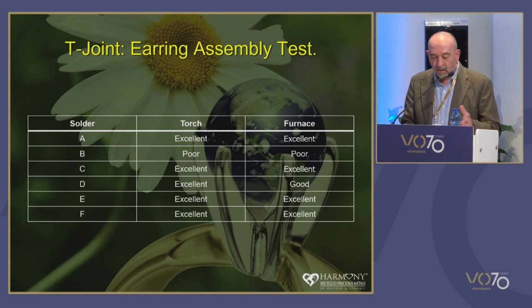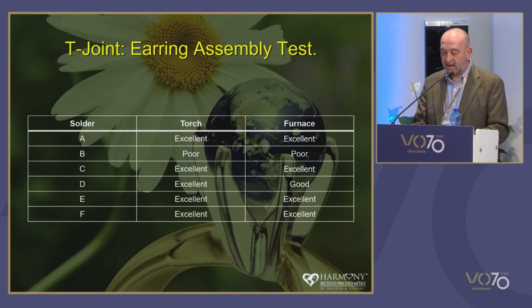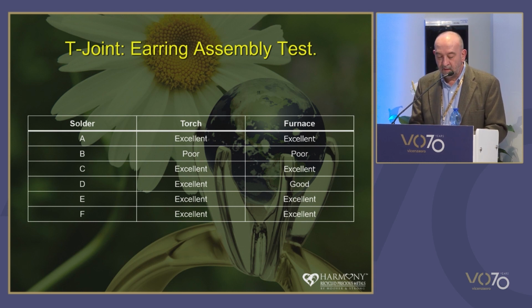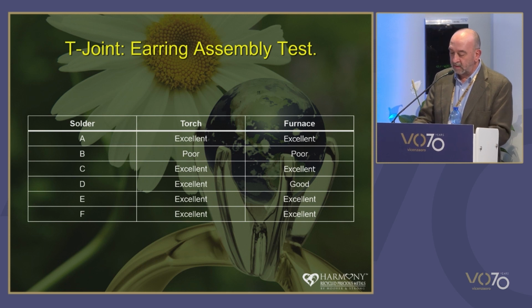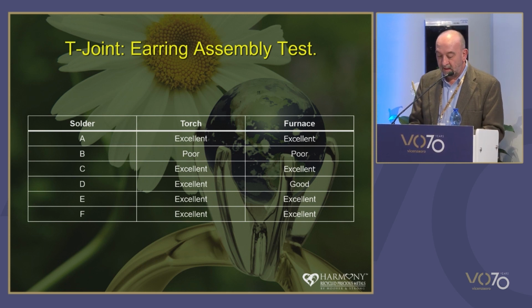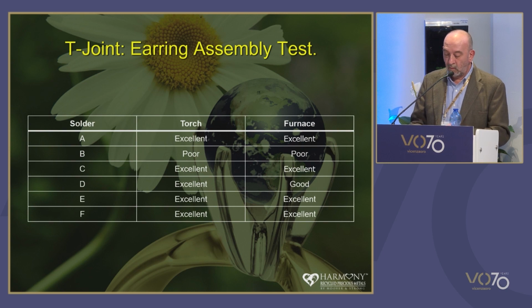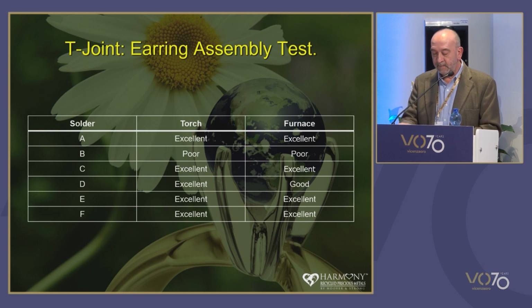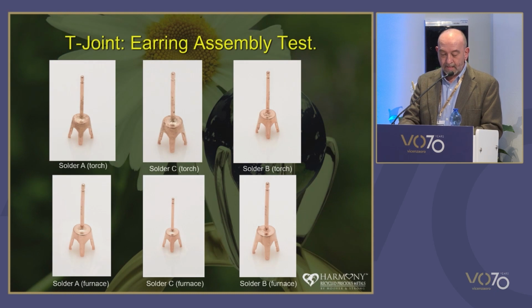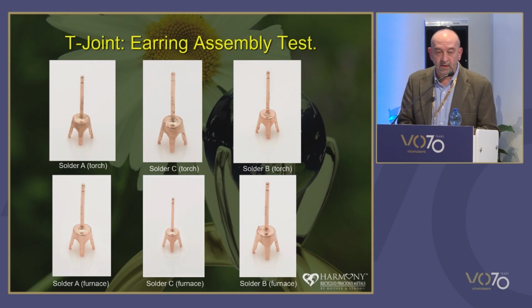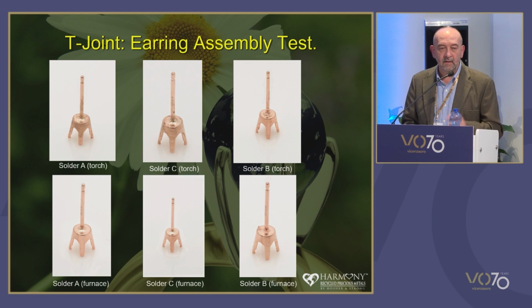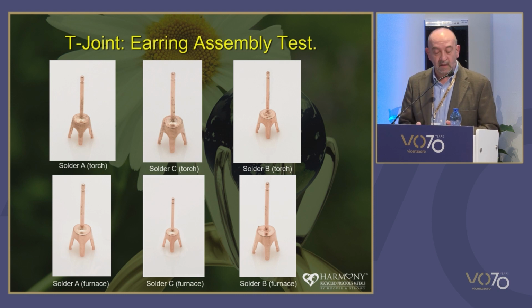And so, unlike the ring sizing tests, all earring tests gave similar results for both torch and furnace soldering, and there was a negligible difference between any cadmium or cadmium-free solders. And again, all except solder B performed well, exhibiting good wetting and good filled joints. And these images can show you, up there on the top left, solder A, either with torch or furnace, soldered very, very well. Solder C was the cadmium-free version of that solder. Again, soldered very, very well. But solder B was awful in both applications.